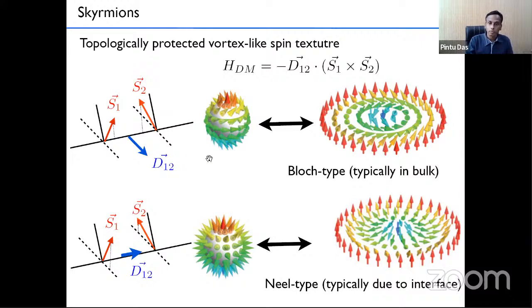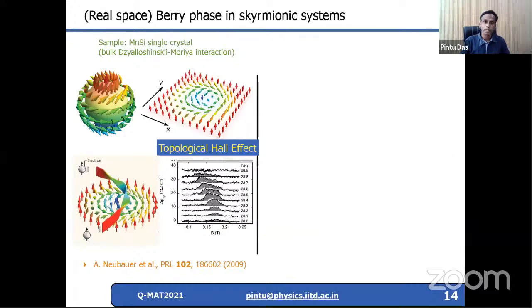There are two types which you usually come across in literature. One is the Bloch type magnetic skyrmions, which are observed in bulk systems, where the Dzyaloshinskii-Moriya interaction is due to the non-centrosymmetry of the crystals. Whereas in thin film multilayer structures, one can artificially introduce interfacial Dzyaloshinskii-Moriya interaction, which leads to Néel type magnetic skyrmions. Our interest is in looking at the transport behavior and particularly the dynamics, because these skyrmions are seen as a potential candidate for memory devices. If they are to be used in a memory device, then one needs to detect them, and detection is necessary in terms of electrical detection. Therefore, understanding the dynamics is important.